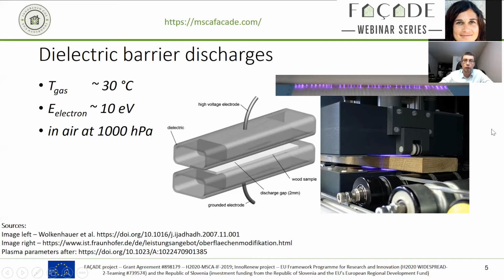Otherwise, this is one of the easier scalable setups. So over a larger surface you can simply increase the length of the electrode, or set up several of these electrodes in a row, and thereby relatively easily go to larger surfaces. However, the thickness of the sample is still limited by the voltage that we can provide. This is something that's very easily operated at atmospheric pressure in air, and we see the gas temperature is, for this kind of discharge, one of the lowest that we can get for plasma treatments. So the temperature increase is typically lower than 10 degrees.